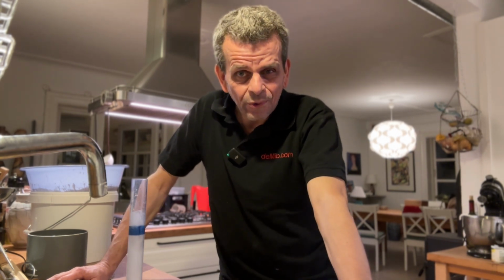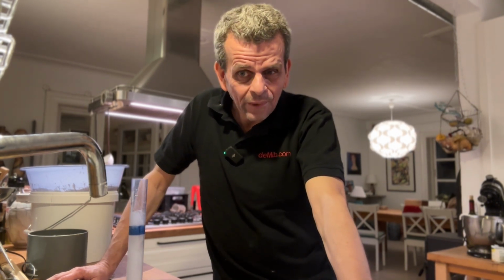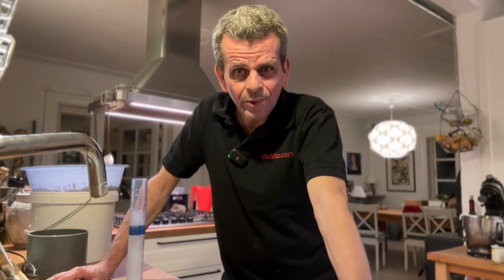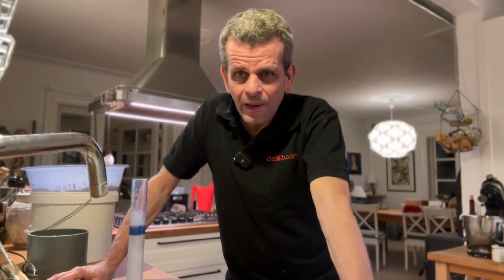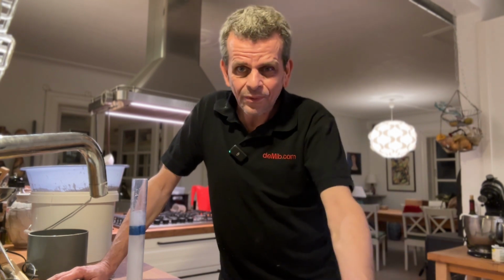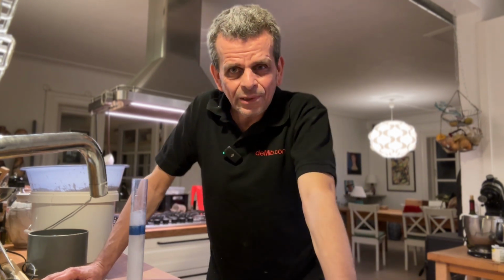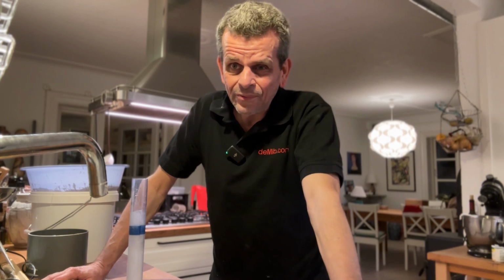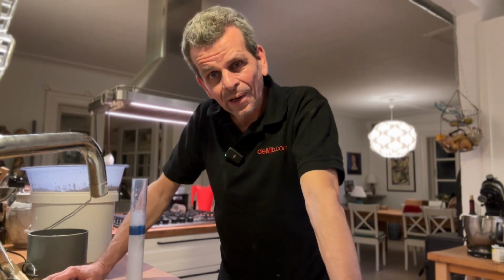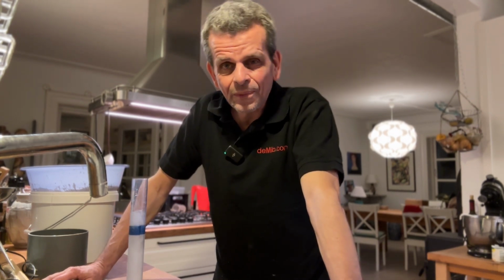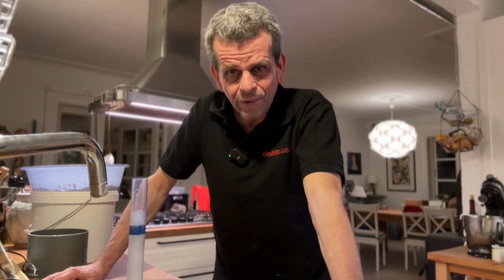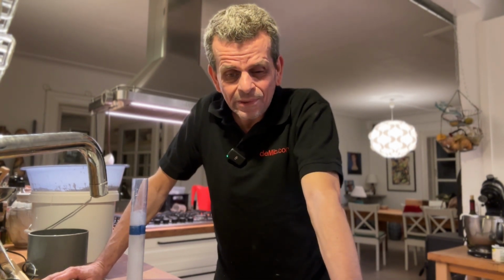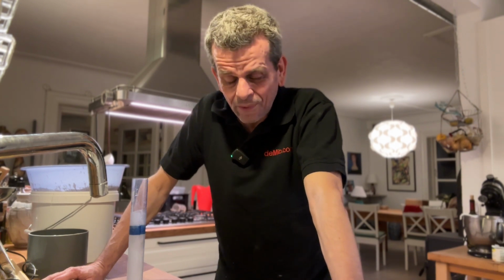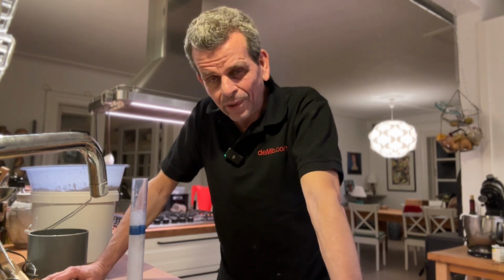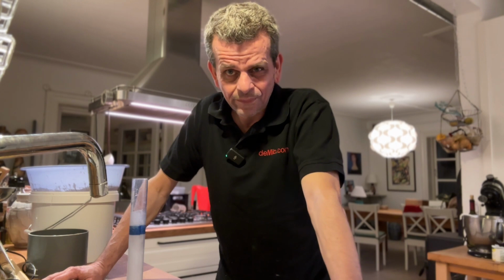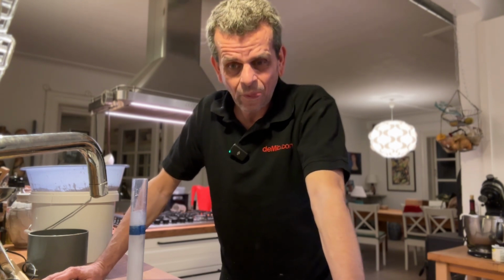Sometimes you can search the forum that I recommend that supports this book, and people have some suggestions there. But if you can't find any, and I couldn't find anything for this glaze, it's typically somewhere between 135 on the low end, and 145 to 148 on the high end. I would probably start out aiming for something like 142, 143. In my experience, a glaze with these kind of ingredients would probably work well for the kind of clay that I'm working with. At least that's what I'm going to try.